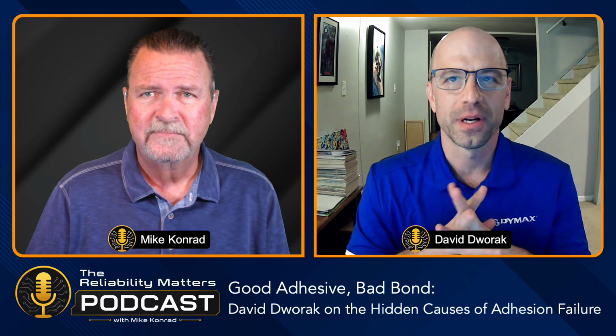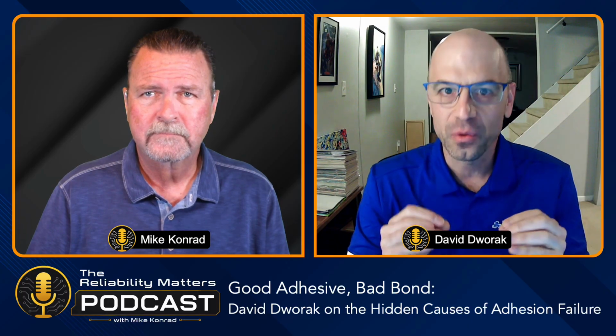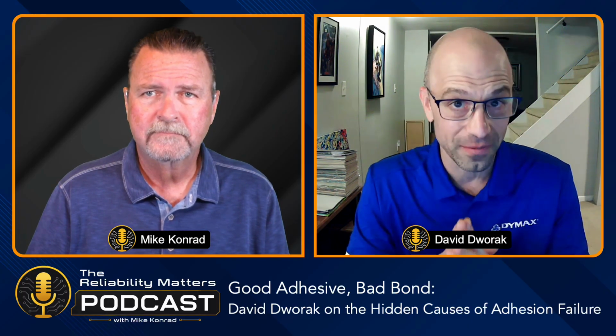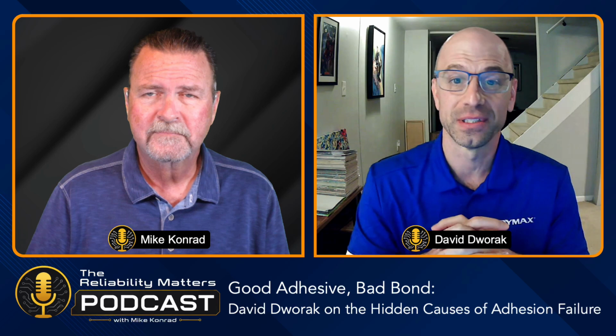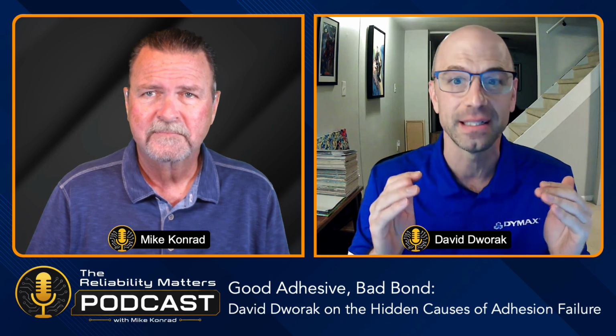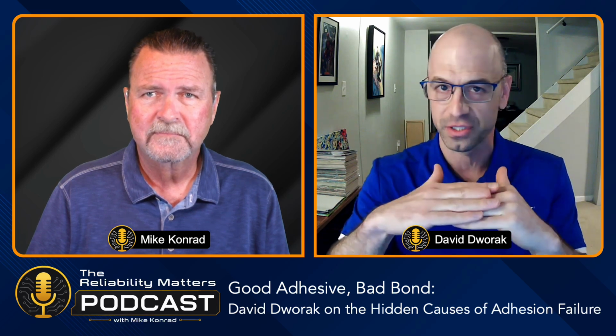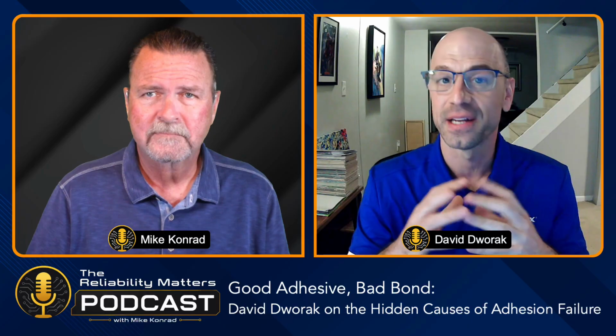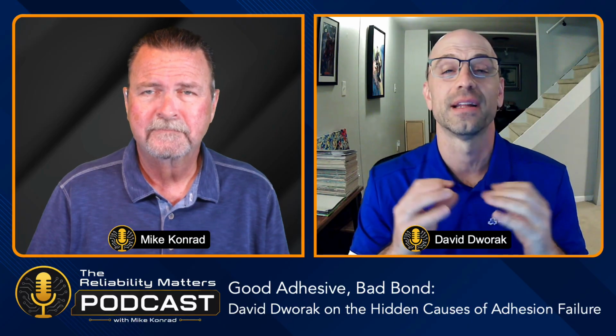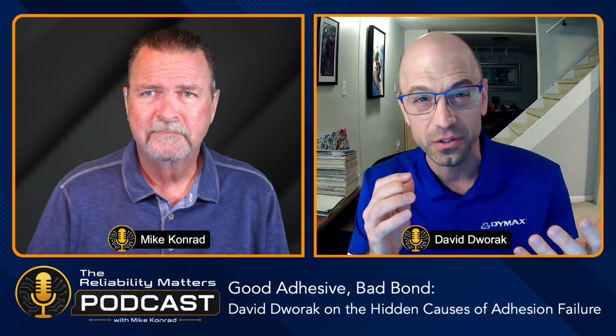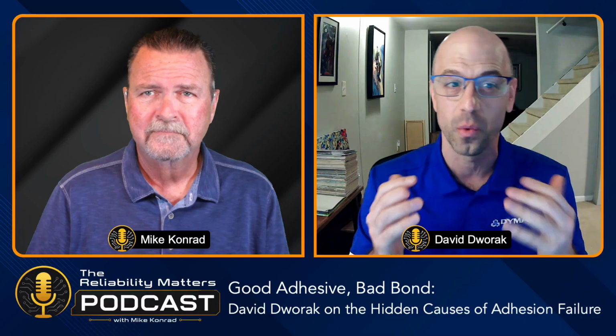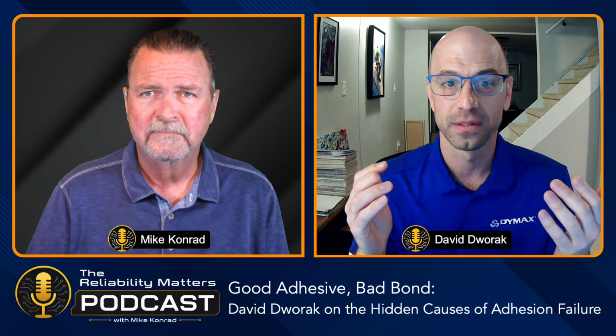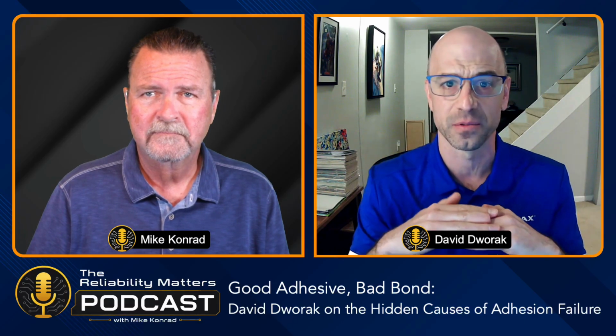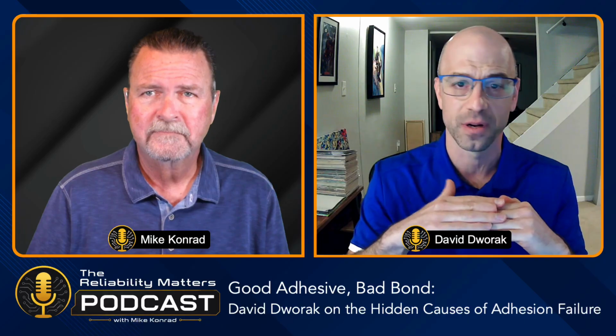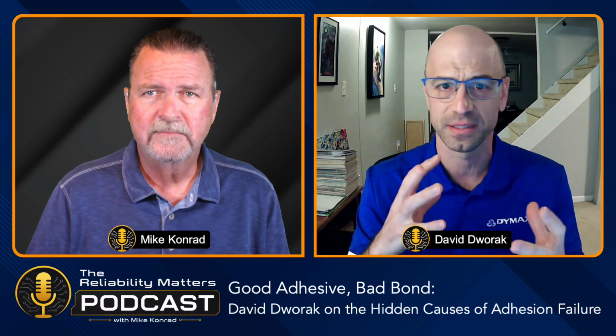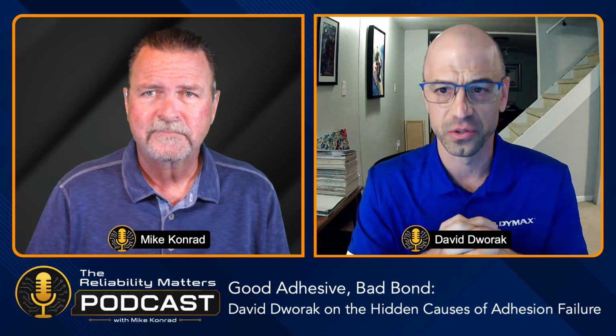Yeah. But I want to go into also how the adhesive failed. That's also a very important factor to consider. So if the adhesive completely delaminated from one of the substrates, it just popped right off, then that is termed adhesive failure. And that suggests a surface energy or contamination or a wetting issue where the adhesive just doesn't want to bond to the substrate. And again, it just popped right off. There's no association there. So that's something you can look into.